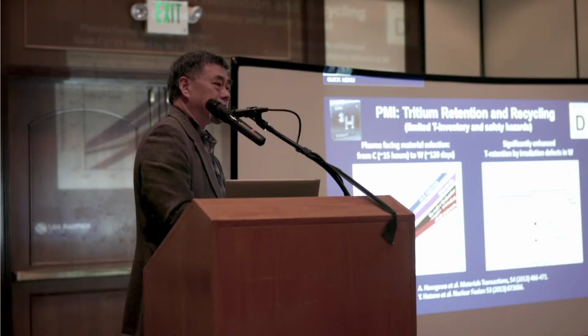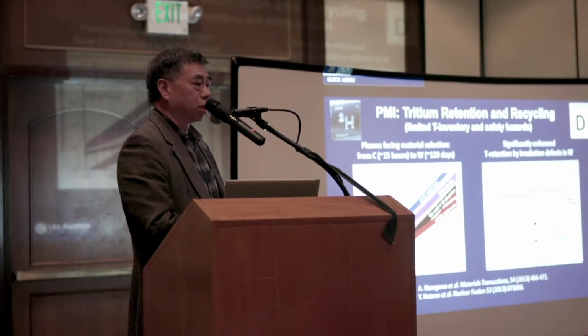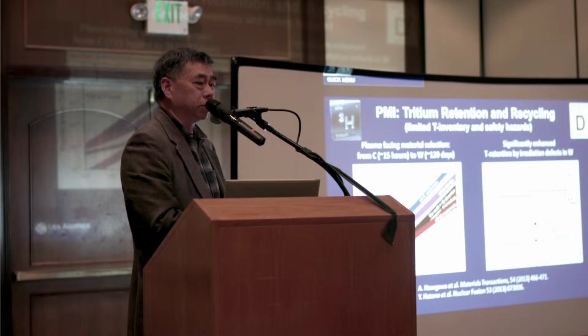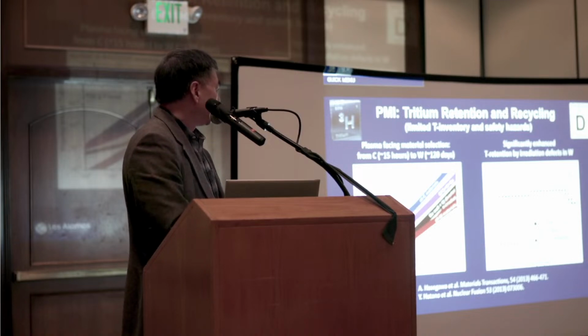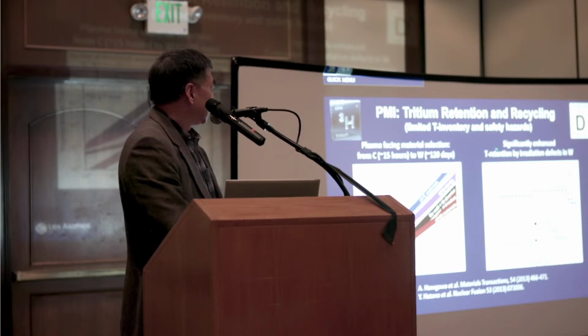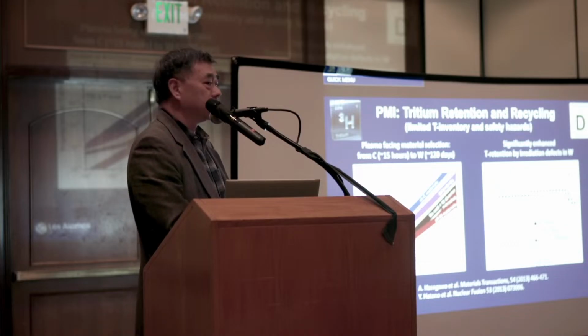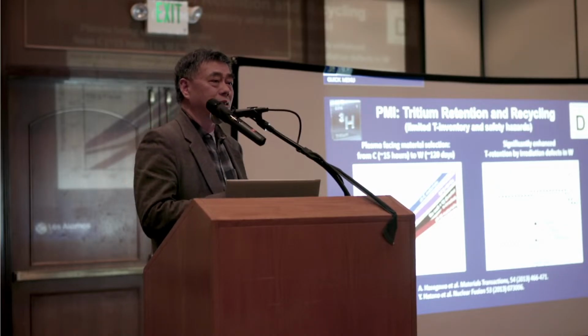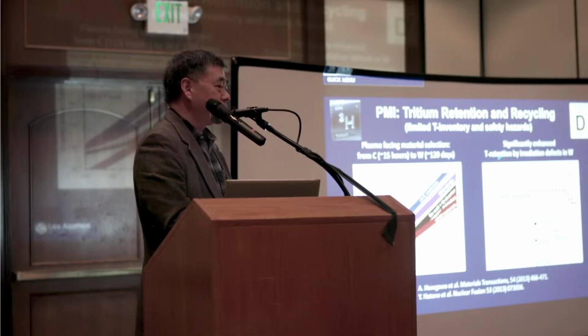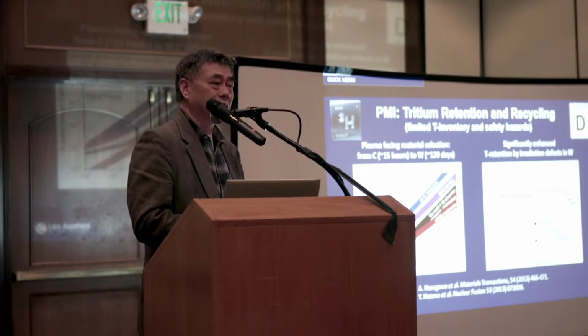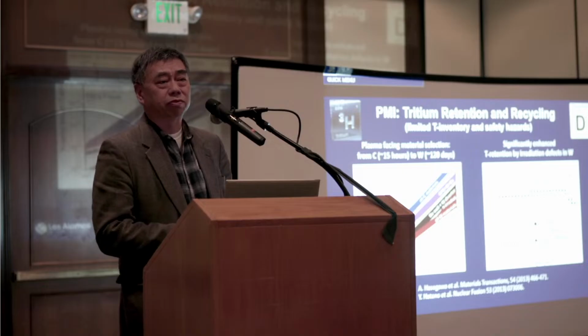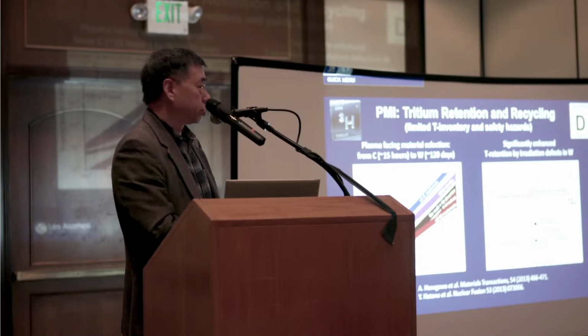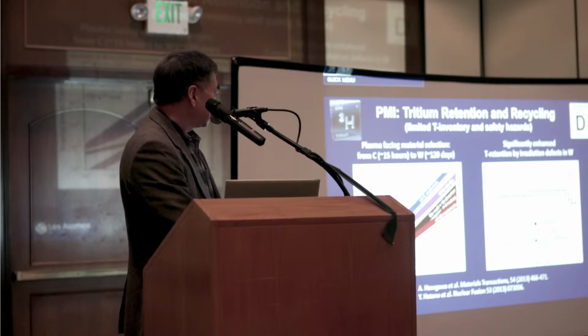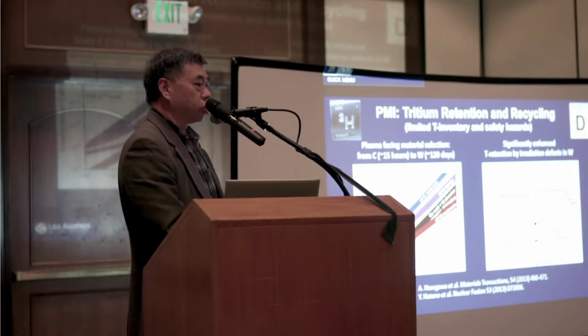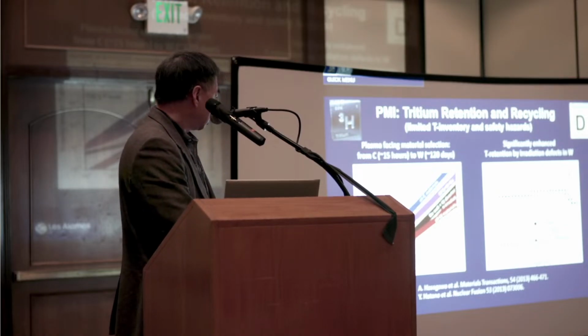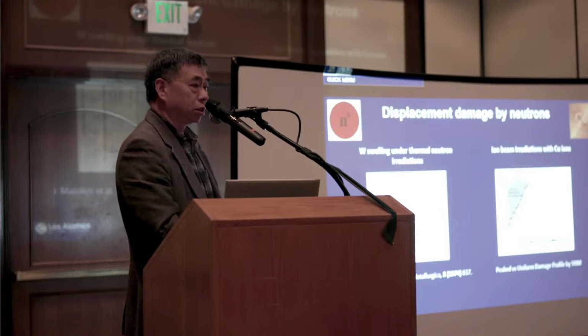Now everything is tungsten, and so you can extend to 100-some days for the experiments that you planned for ITER. Now an issue comes very quickly. Yes, the tritium retention rate is pretty low in tungsten, but that's for non-damaged tungsten. Once you have neutron damage in the tungsten, you produce a lot of defects. Those defects become trapping sites for the tritium. So even with very little damage, the retention rates jump by an order of magnitude. So that's challenge number 1 with tungsten.